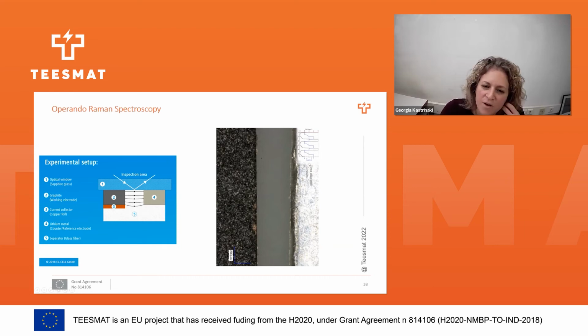So we can start with the charging. You can see the lithium ions. It has been charged at a very, very slow rate. So you can have a charging, then discharging, then the formation of the lithium dendrites here, and then again it begins to charge. You can see the changing of the color due to intercalation. And then again we have discharging, again formation of the lithium dendrites, and then cycling again. So actually you can understand that we can observe the chemical composition. Once we have the laser beam on top, we can understand the changes in the chemical composition by the different spectra that we get.